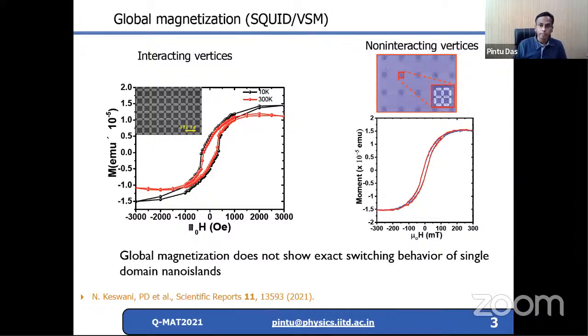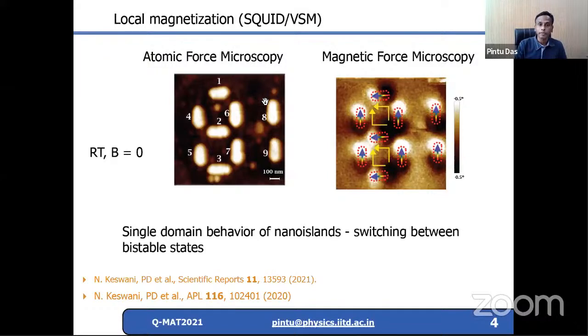If you want to understand switching behavior, you need to actually probe the individual nanomagnets. Since these nanomagnets are very tiny, you need a highly sensitive tool to sense their magnetization. Typically in experiments, you perform imaging using, for example, magnetic force microscopy, which a typical lab will have. Here I show you nine nanomagnets. Topography is shown by atomic force microscopy images, and the corresponding magnetic force microscopy images show that they are nicely single domain. That means there will be switching between the bistable states. This is what one actually observes in magnetic force microscopy.